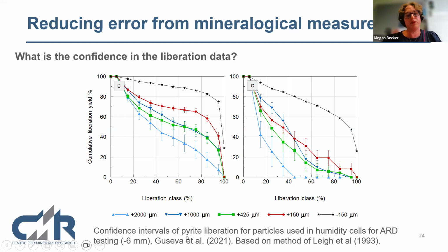This comes from a master's student of mine, and she was looking at acid rock drainage testing. The standard for acid rock drainage testing is minus 6 millimeter material. So she sized it into a number of size fractions, and we measured the particle properties in each of the size fractions. For the material that is sub 150, shown in black, the error bars, the confidence limits, are very small. The plus 150, they're getting a little bit bigger, but if you look at the plus 2 millimeter material, big error bars. That's because we have to present so many more particles, it takes so much longer for us to analyze, because we're mapping so many more particles, or we need to.